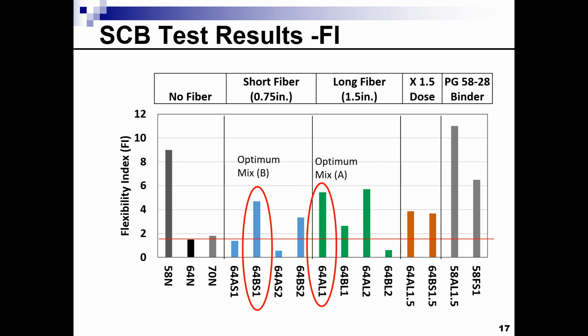As you can see here, first of all, I would like to note that we have different fiber lengths and doses. If we go here, the first two numbers indicate the type of binder. The next letter indicates A or B, A for fiber A, B for fiber B, and S for short. The one indicates the dosage recommended by the manufacturers. We also had the N, which means it was a non-reinforced mix. So we have a 64, a 70, and a 58.